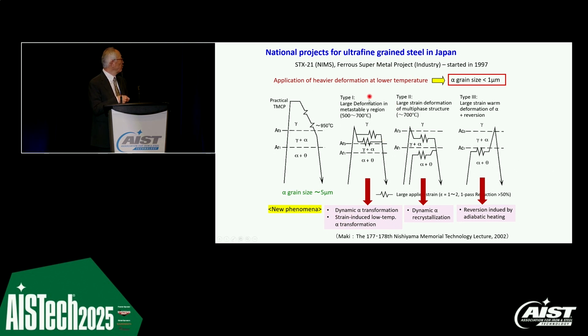For type 1 case, we mainly have the dynamic transformations. And for this case, of course, this is two-phase field deformation. We can have the dynamic recrystallization of the ultrafine grain to obtain ultrafine grain materials. In this case, as I mentioned, low temperature and applying the heavy deformation, we can have the sharp increase in the product temperature and get the adiabatic heating reversion. By having such a new phenomena, we could reach a ferrite grain size less than 1 micron.